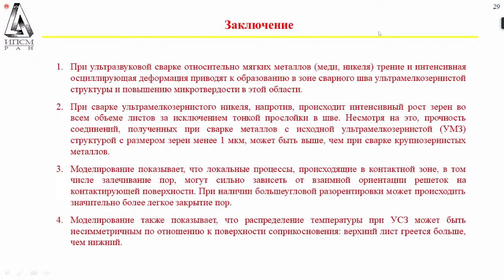And these are the main conclusions that we have obtained. I would like to note that mainly it's that we can weld at the ultra fine grain state. It gives higher quality joints. There are some peculiarities about this orientation, and secondly, the spreading of temperatures at ultrasonic welding can be non-symmetrical, so the higher layer will heat way faster.